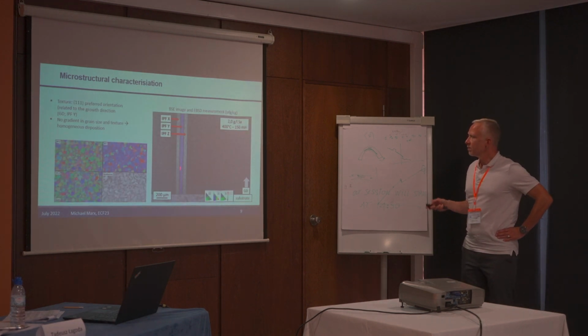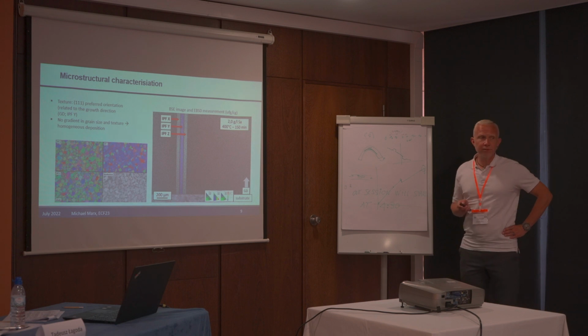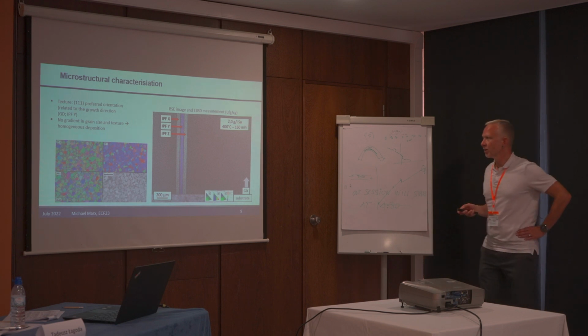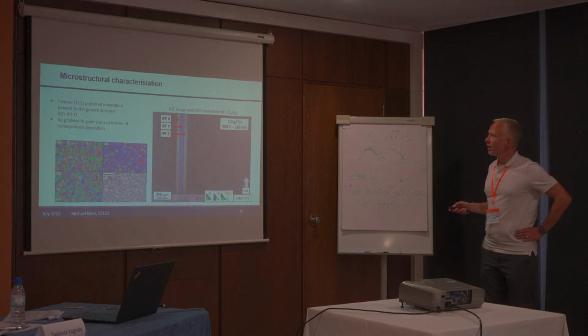We have done this through the whole thickness. Here there's a substrate. Here you can see it's quite homogeneous. We have a texture, as you may see from the color of these EBSD maps we have done, but we do not have any gradient in the grain size in this direction here.